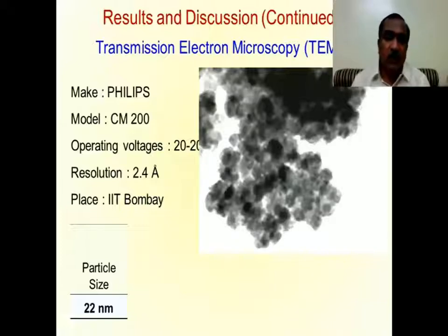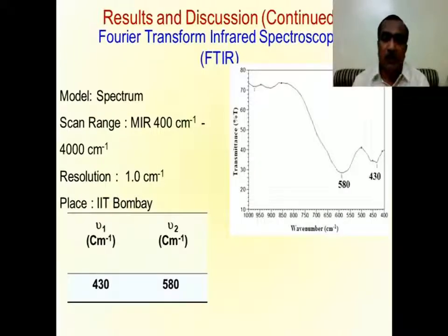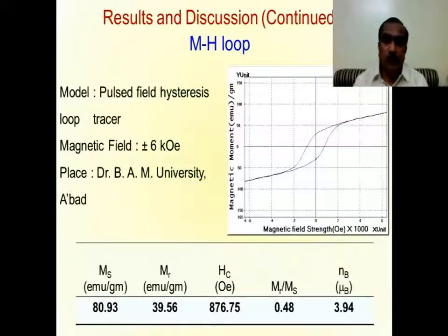Similarly, the FTIR was recorded here, and it is taken from IIT Mumbai. This is the FTIR spectrum, which represents two absorption bands, one near 430 and another at 580. So these are the characteristics of the ferrite. You will observe there are only two broad peaks at around 400 and 600, that indicate the formation of the cubic spinel structure of the ferrite nanoparticle. This is the magnetization, the important property of the ferrite, that is the magnetic property. It was recorded in our laboratory using a pulse field technique.